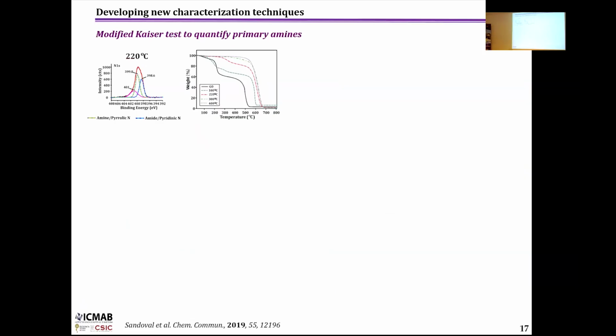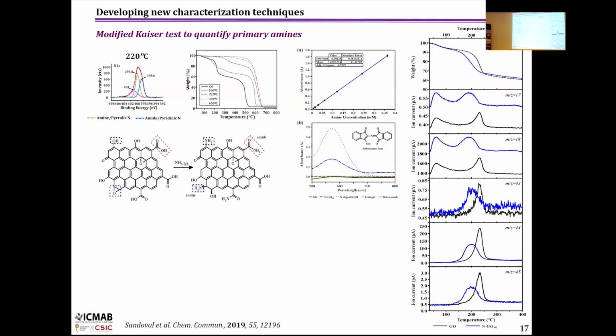Okay, continuing with the development of new characterization techniques and also obtaining proper characterization of these systems, we observed that XPS, even though it's a very useful technique, has a problem, and that is that the area where the binding energies of the aliphatic groups appear overlaps with the signals of pyridinic and pyrrolic systems. So we used a modified Kaiser test, developing this system using an adduct to determine the presence of primary amines in the system. This characterization enabled us to discern between the aliphatic groups present in the material and pyridinic or pyrrolic ones.